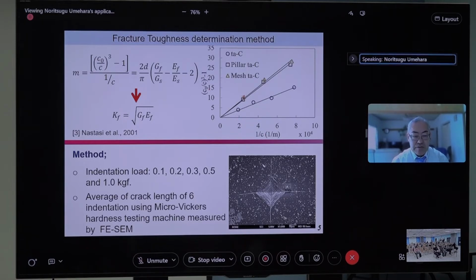At first, Dr. Dean, who is now in Malaysia, did such an experiment: ta-C, pillar ta-C, mesh ta-C. It means different structures of DLC. He found a very good relationship like that. From the gradient, the M value, we can get this GF. If we know the GF, we can estimate the fracture toughness of only the coating.